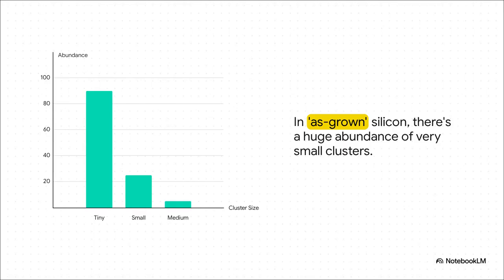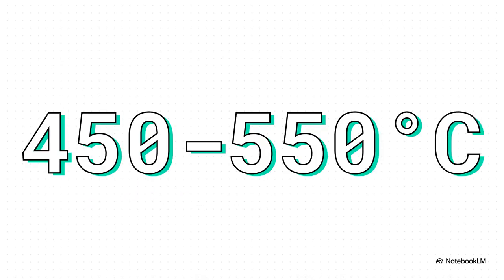So right after a silicon crystal is first grown, it's just swimming with these tiny, really unstable oxygen clusters. What this chart is showing you is that there's a ton of them, but they're all super small. And at this stage, they're not really useful yet. In fact, they can just dissolve right back into the silicon. They're just potential, waiting for a trigger. And that trigger is temperature.